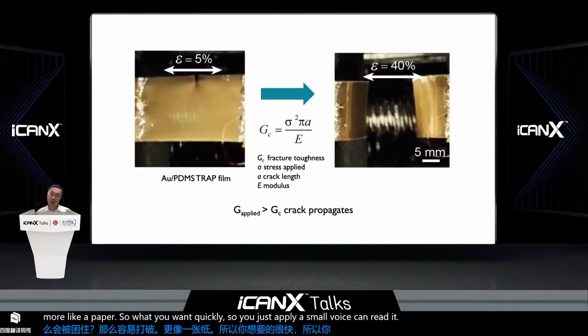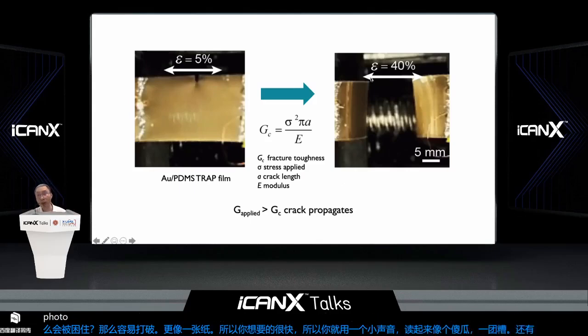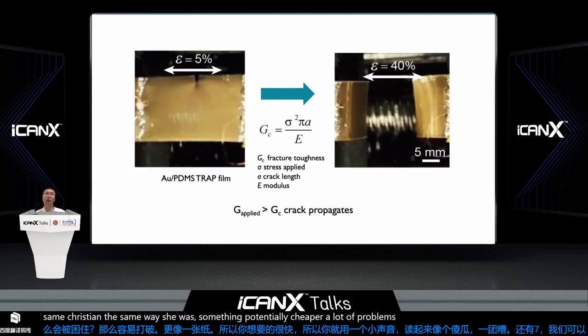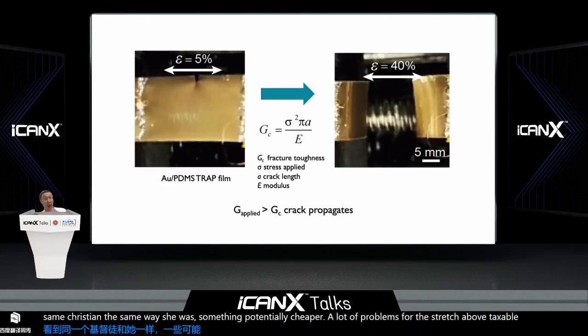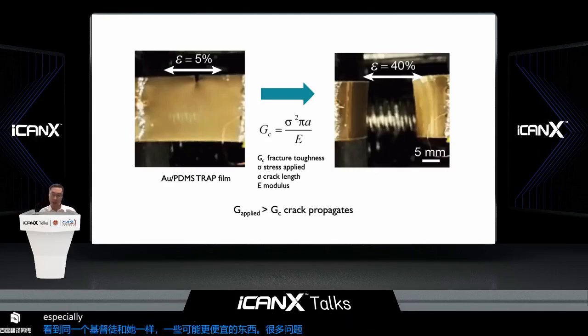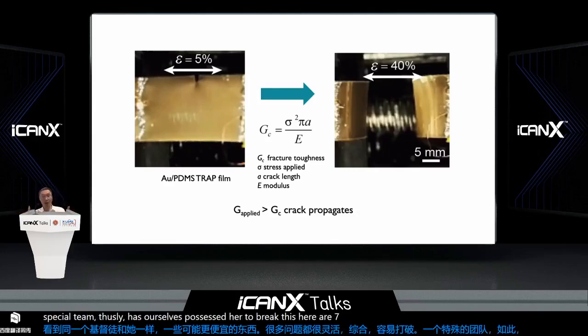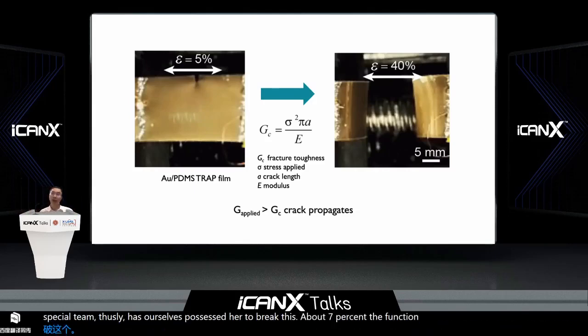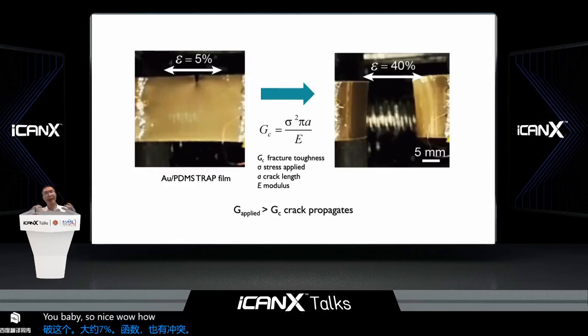Like the gold PDMS, it's also similar. The crack migrates. You can see from a 5% crack here, at 40% it immediately breaks already. So that's something that potentially gives us a lot of problems if we go for this kind of stretchable, flexible, integrated device. You don't want a device that is easy to break, right? Especially for our skin. The skin has about 70% stretchability. It means you need to ensure the device still functions well at about 70%. And in other organs, they even require more than 200% stretchability. So how can we really prepare anti-tearing electrodes? This also gives us challenges.